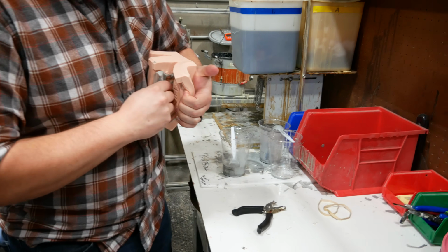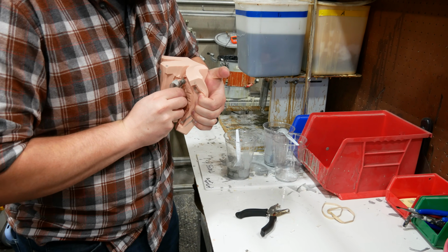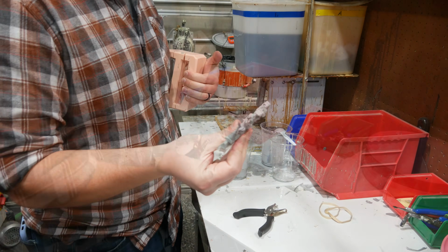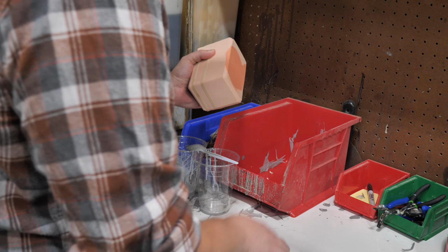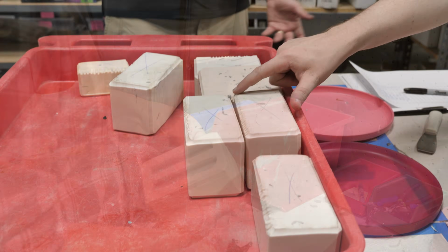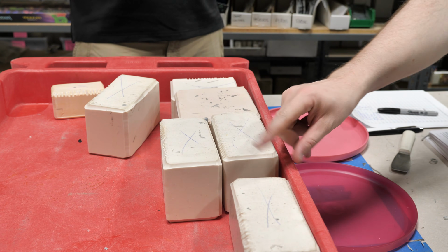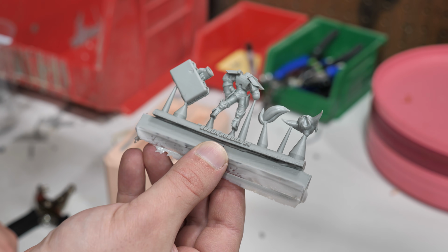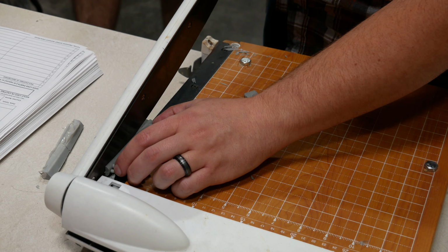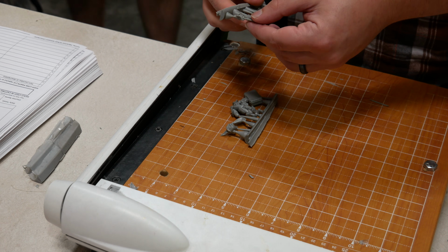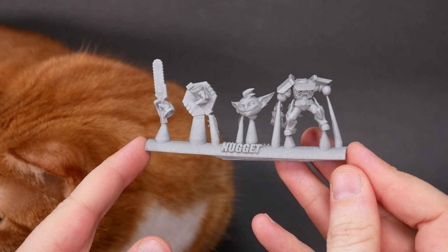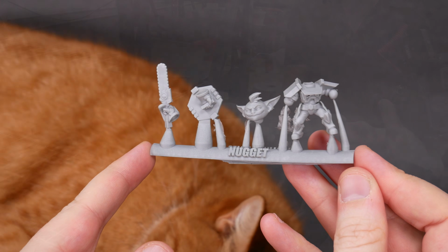These soft silicone molds give incredible detail, but they start to degrade after about 20 uses. The team clips a notch onto each mold after each use, so that they can tell when it's time to retire it and make a fresh one. There's always a bit of excess resin at the top of the mold where it funnels down into the sprue. This solid reservoir gets chopped off and thrown away, and then the sprue is ready to be packaged and sold.